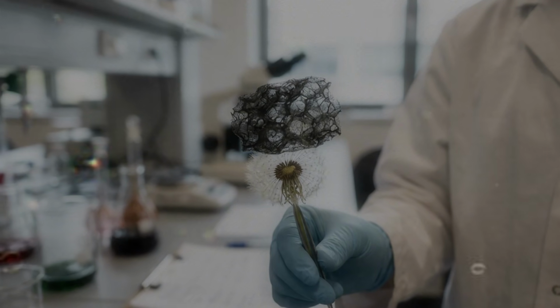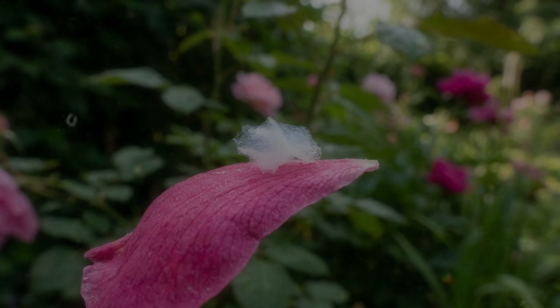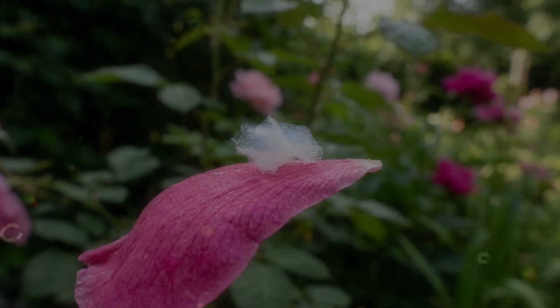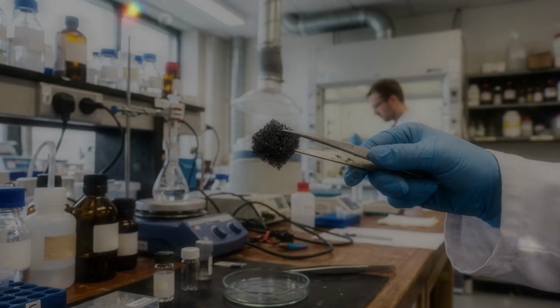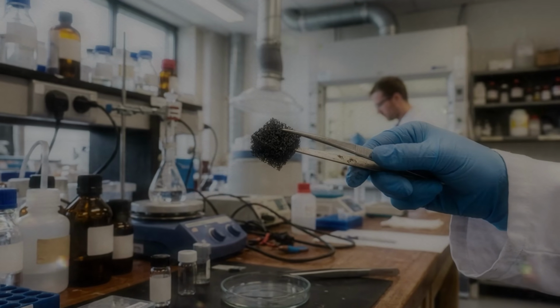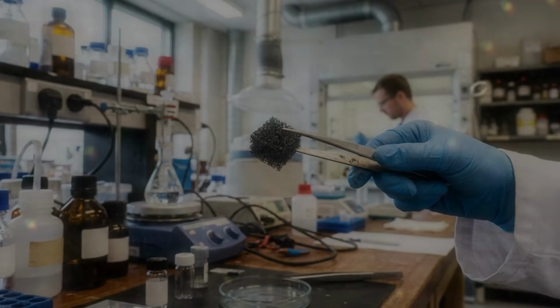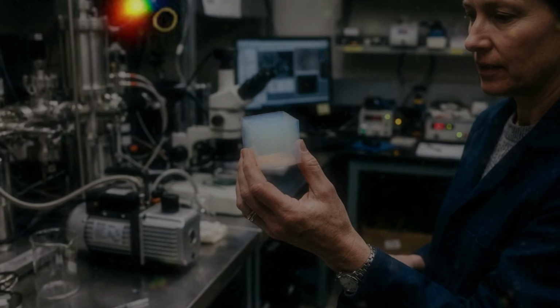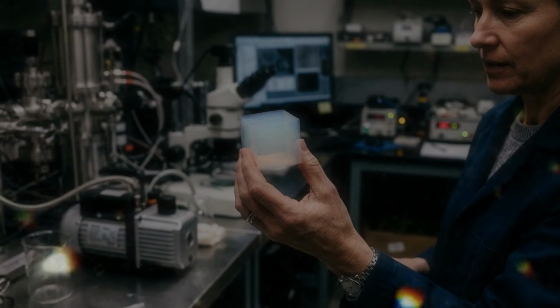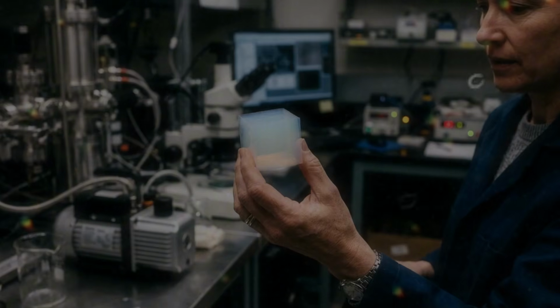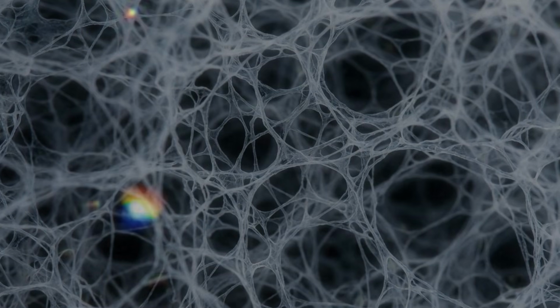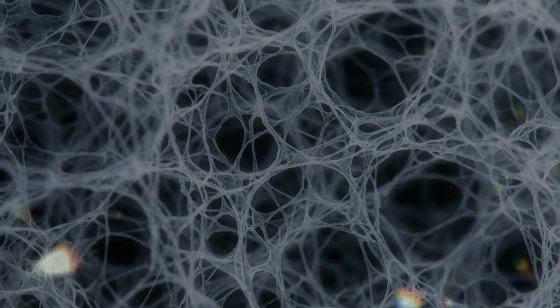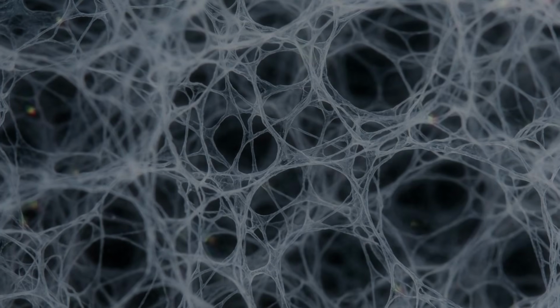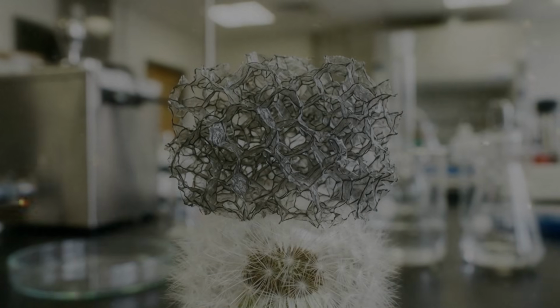Most aerographene has open pores. Air enters those pores and becomes part of the sample as it sits in the atmosphere. The material does not seal a large volume of a low-density gas away from the heavier air outside it. A balloon floats because its outer skin encloses a gas that weighs less than the air displaced by the entire balloon. The surrounding atmosphere pushes upward with a buoyant force. If that upward force is greater than the total weight of the skin, the string, and the enclosed gas, the balloon rises. An open aerogel works differently.